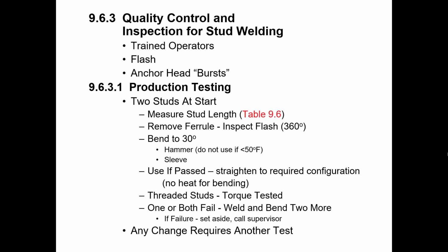Any change in any of those variables, whether it's the thickness of the plate, the diameter of the stud, the length of the stud, any of that, requires that you treat that like you're restarting. So you've got to do two more.